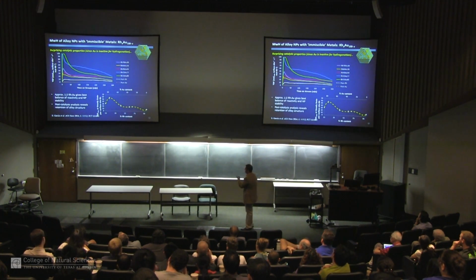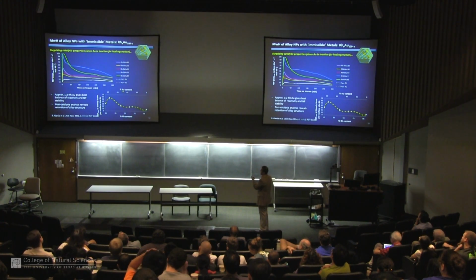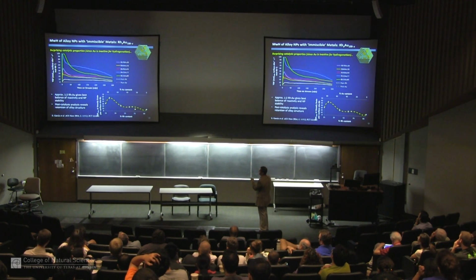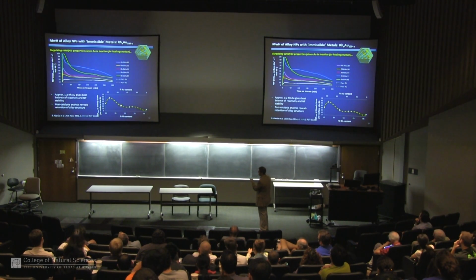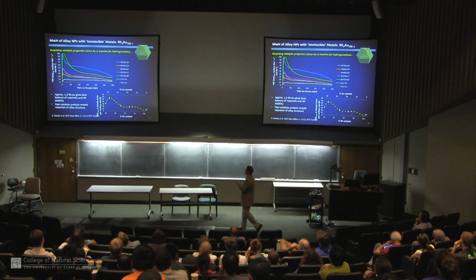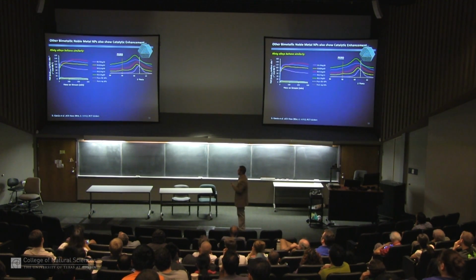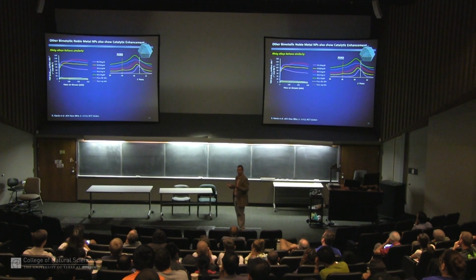We can see the correlation between composition and turnover. You see that you still need more rhodium than gold to get active catalysis, but they are pretty good catalysts. And even more so, this is our favorite alloy by far, rhodium silver. You can take rhodium, very expensive, dilute it down with silver, and make an even more active catalyst than you started with. And we found here that this is way off scale.